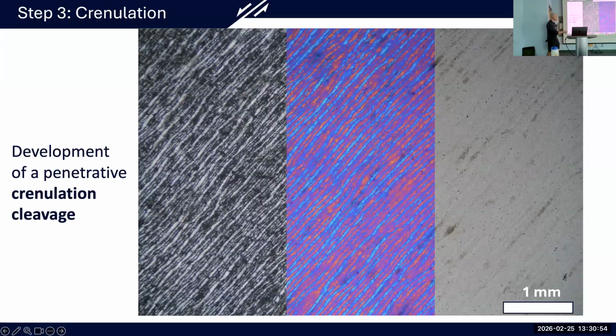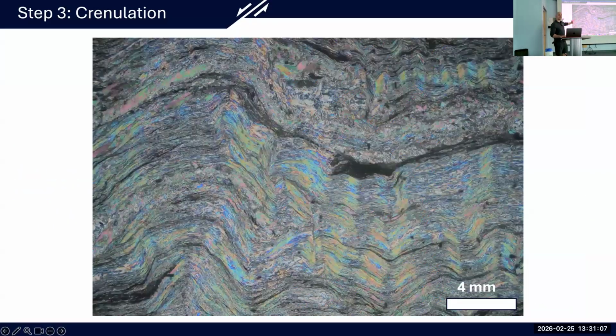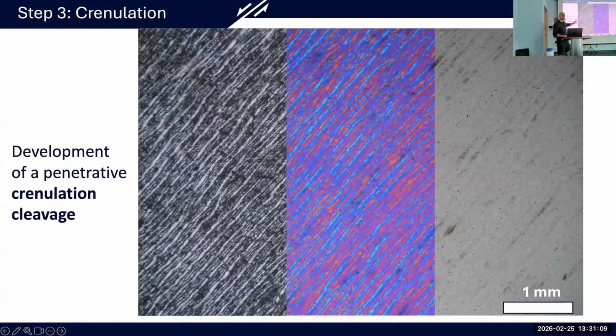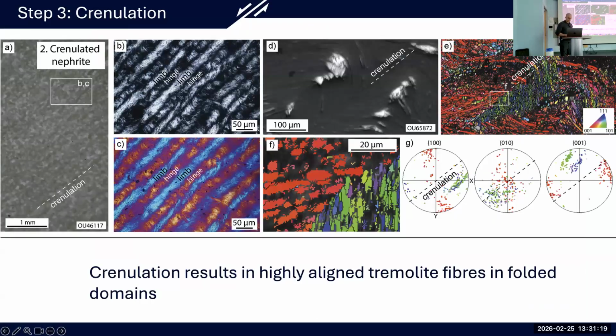And we can see here that what this image is telling us is that we have a strong alignment of our nephrite needles, but in these fine bands. And these fine bands represent that same folding that we saw before, but taken to an extreme. So that folding has occurred all the way across here, and the axes of our fold are diagonal across this image. If that's difficult to imagine, let's look a little bit closer.